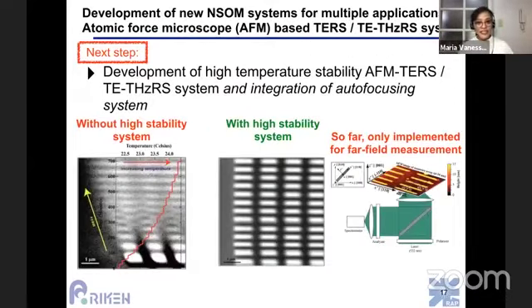Now, to clearly see how this autofocusing system works, let me show you this very nice slide. Without the high stability system, you can see that as the time increases, the temperature of the room also increases, and that also causes some defocusing because of the change in the environment. At the start of the measurement, you still have a more or less focused image, but as time goes by, it becomes so defocused that you cannot identify what kind of structures you are trying to make or to image. But with the high stability system, you can clearly see these strained silicon nanowires, which are nicely spaced from each other.